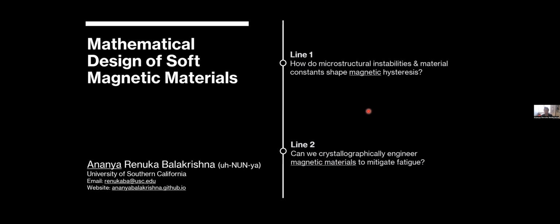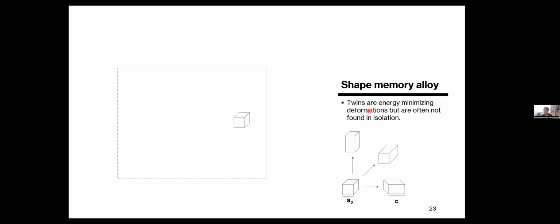Shape memory alloys are structural materials that, if you heat and cool across a phase transformation temperature, show an abrupt transformation of their unit lattices, say from a cubic phase to a tetragonal symmetry. You can have three different variants during this transformation. On the left is a sketch of a shape memory alloy, which in its high temperature phase, the austenite phase, has a cubic symmetry.